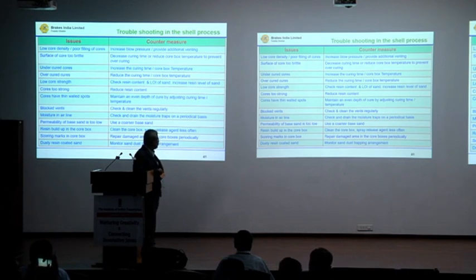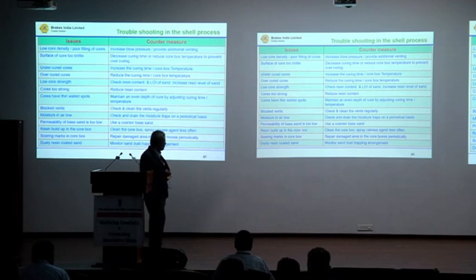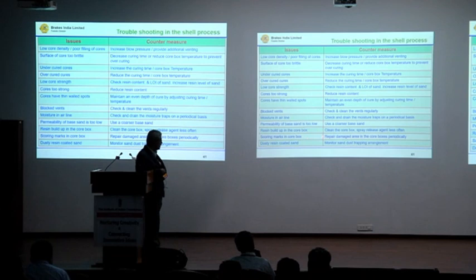If permeability of sand is too low, use coarser sand. For resin buildup in the core box, clean the core boxes and spray release agents less often. For scoring marks in the core box, repair the core boxes at regular intervals.